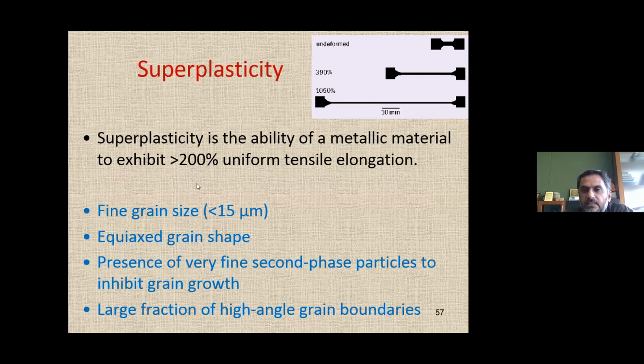And if you generate a tensile specimen from that region, from the stir region, this is your original specimen, right? Please follow the cursor. Then that specimen is subjected to tensile loading, but at high temperature. So you realize that the material is displaying elongation which is more than 200%, right? You see in this case, it is 1050. So in that case, you can say the material is superplastic. The material has the superplastic behavior.